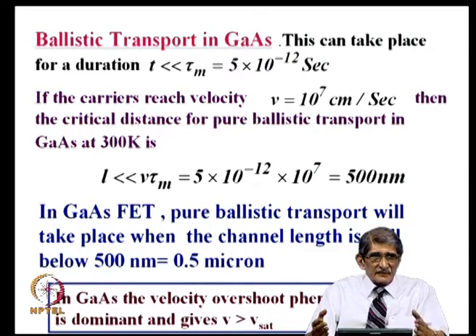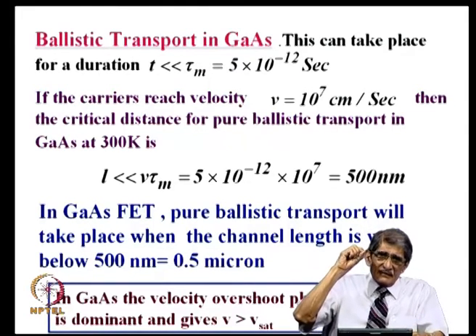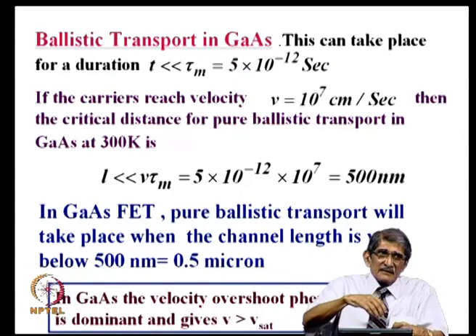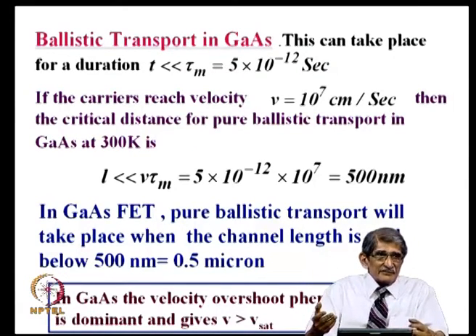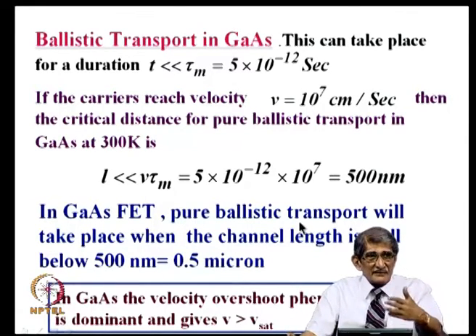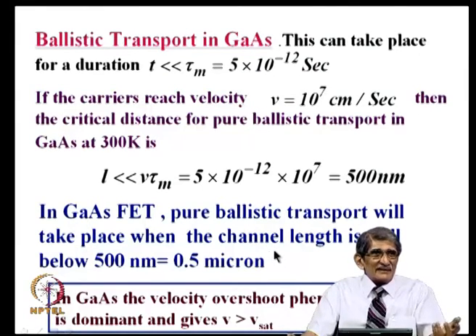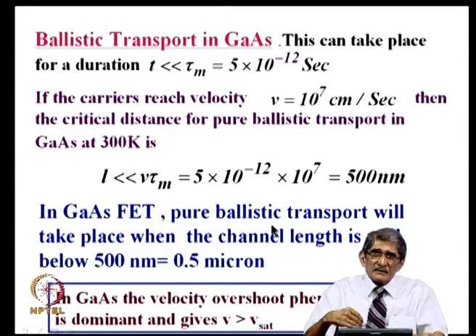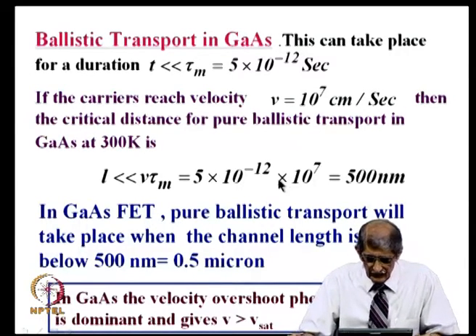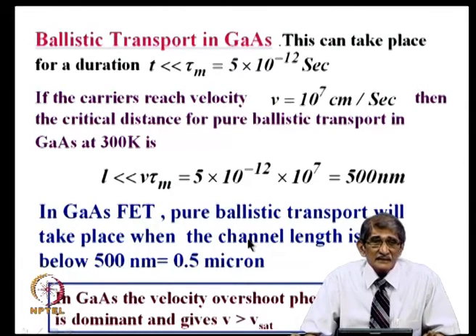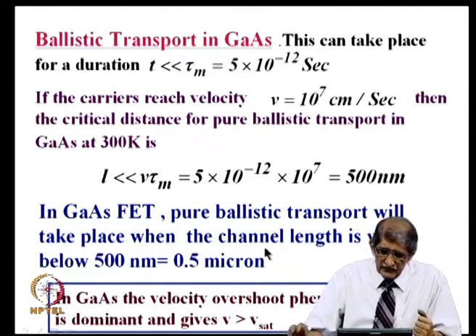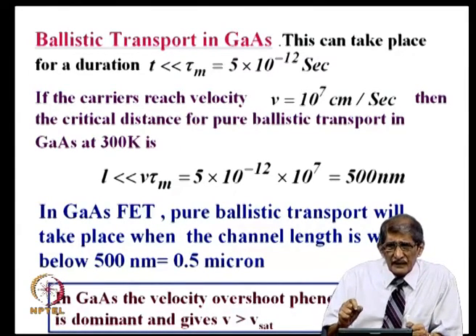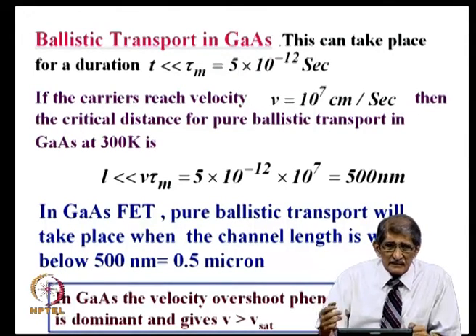So, if the carriers are injected into that gallium arsenide channel in that short period of time before it gets scattered, if it is suddenly injected into the channel where the high field is present, it will get accelerated to high velocities higher than 10^7. That means, in gallium arsenide you will have velocity overshoot effects, like transient effects in LC circuits, etcetera. Okay? There will be overshoot effects, because before it comes to steady state, the velocity goes over and above the saturation velocity, and that may give rise to an injection velocity much more than the saturation velocity. So, that is why in the case of gallium arsenide devices, you may encounter drain currents which indicate that the injection velocity of electrons is much more than the saturation velocity. That is because of the velocity overshoot effect.